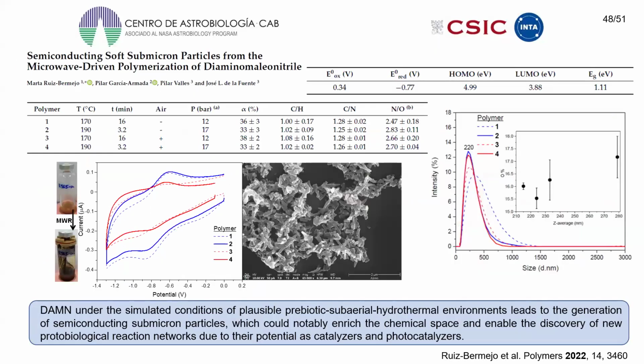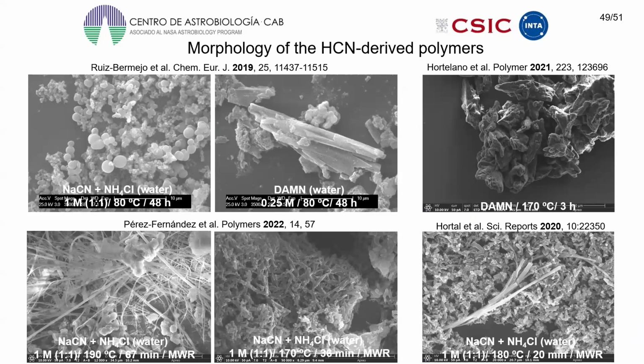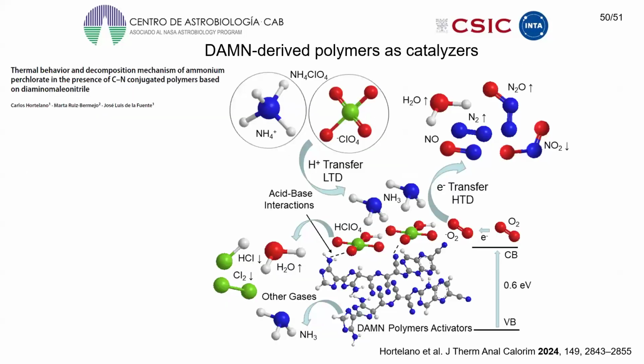One step beyond, we also tested the hydrothermal polymerization of DAMN under subaerial conditions. In this case, we assessed the formation of submicron particles with electrochemical band gaps similar to those of inorganic semiconductors. This result has interesting prebiotic implications, since these types of particles could notably enrich the chemical space and enable the discovery of new protobiological reaction networks due to their potential as catalysts and photocatalysts. Note that the morphological properties of the hydrogen cyanide derived polymer can be modulated by the reaction conditions, and that the DAMN polymer exhibits catalytic properties for both hydrogen peroxide reduction, as previously commented, and for the thermal decomposition of ammonium perchlorate, recently described.